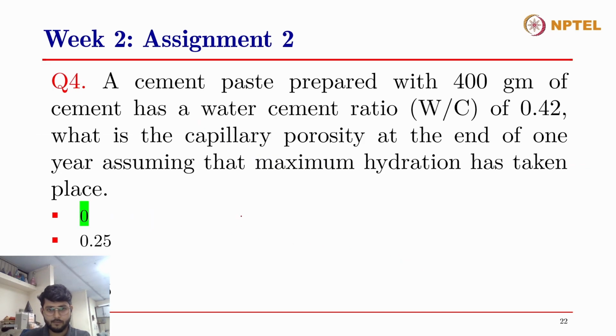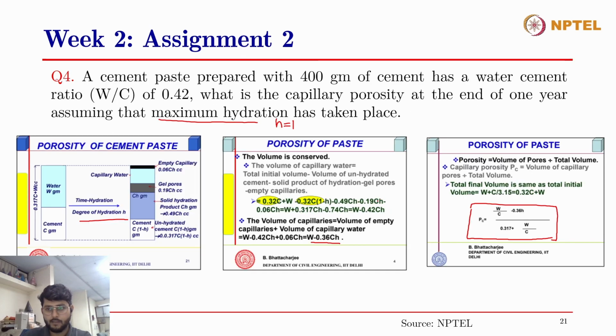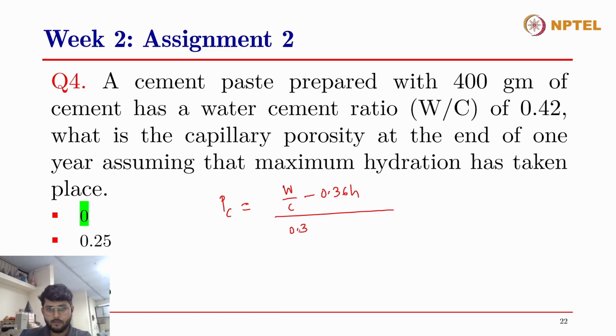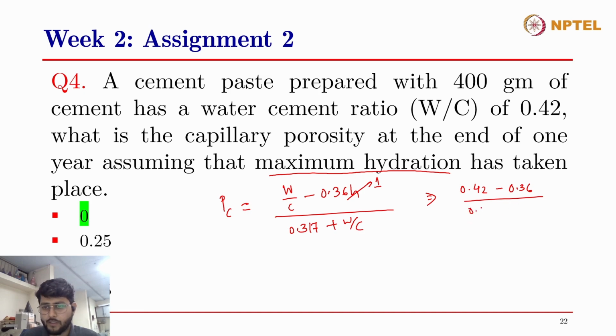So the final expression for the volume of capillaries is W minus 0.36 H, and porosity is defined as volume of pores divided by the total volume. Therefore the final expression for capillary porosity will be volume of capillary pores divided by total volume, and this is the expression. PC equals W by C, meaning the water to cement ratio, minus 0.36 H divided by 0.317 plus W by C.